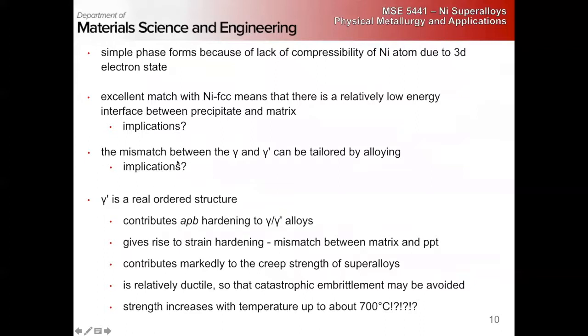The mismatch between gamma and gamma prime can be tailored by alloying, right? So we can play a trade-off between the amount of strengthening we get versus the stability of the microstructure, right? Because the more we play with the coherency, we're going to affect how easy things are to cut, but we're also going to drastically change our interfacial energy and change our coarsening kinetics, right?